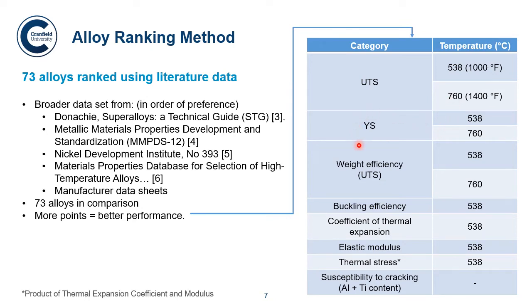Then we have yield stress as well, at the same two temperatures. Then we have weight efficiency at the same two temperatures. Then we have buckling efficiency just at 1000 Fahrenheit, as well as coefficient of thermal expansion, elastic modulus, and thermal stress, which we'll get onto a bit later. And we also rank the susceptibility to cracking, which is an estimate based on the aluminium and titanium content of the alloys, which isn't ranked as a temperature.